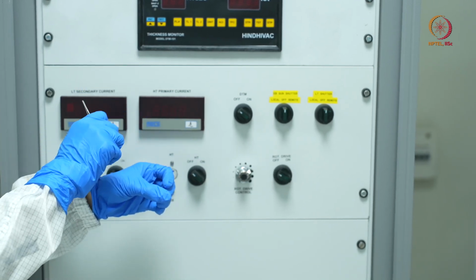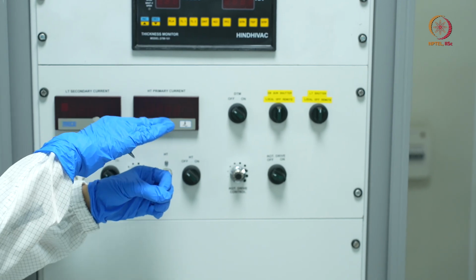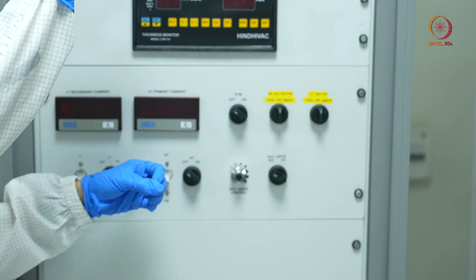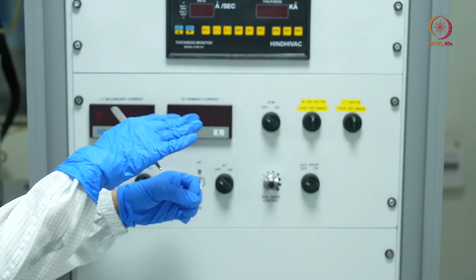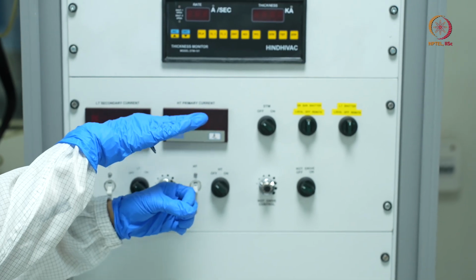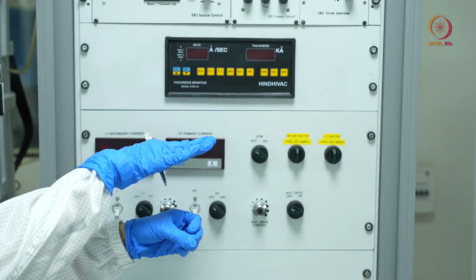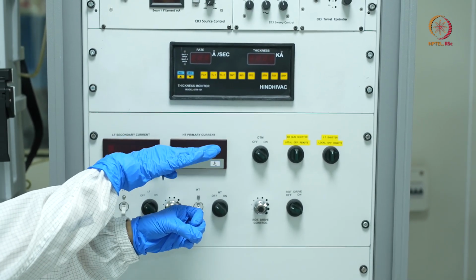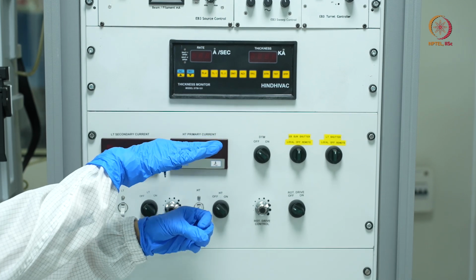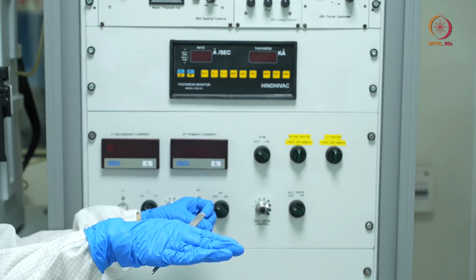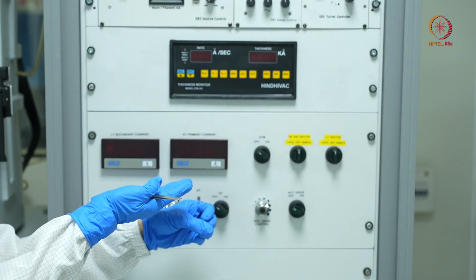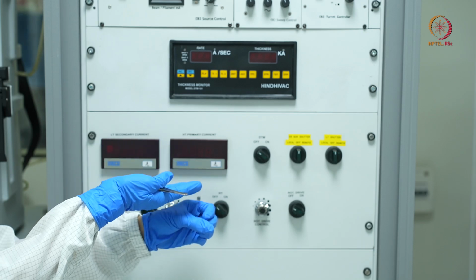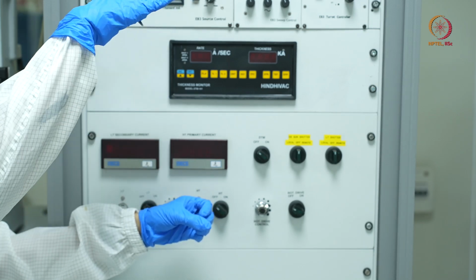It will be glowing after a point, and the material inside the basket will start melting. At that time, I don't want any deposition to happen onto my substrate which is kept above. For that reason, I have kept a shutter. Till my material is melting, I'll keep the shutter closed. Once the material is melted, I'll open the shutter, and the vapors coming out of this basket will settle down onto my substrate.